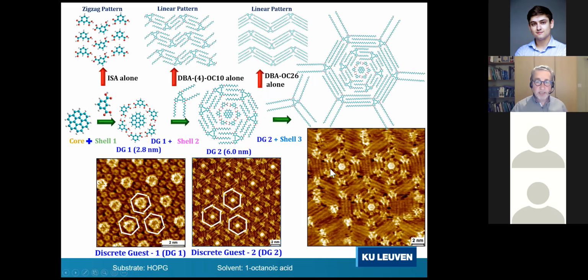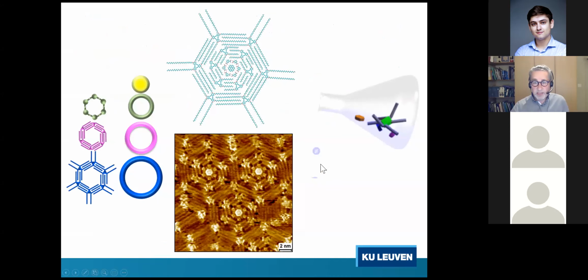There is, of course, an aspect of beauty in it, but there is also an aspect of science in it. Science, because by doing so, and I don't give you all the details here, we learn quite a bit about the thermodynamics involved, but also about the kinetics and kinetic traps that can actually play a role in the successful formation of this kind of networks. And all of this, again, I repeat, is simply achieved by mixing these 4 different molecules in very well-chosen concentrations in an appropriate solvent and bringing such a solution at the liquid-solid interface.